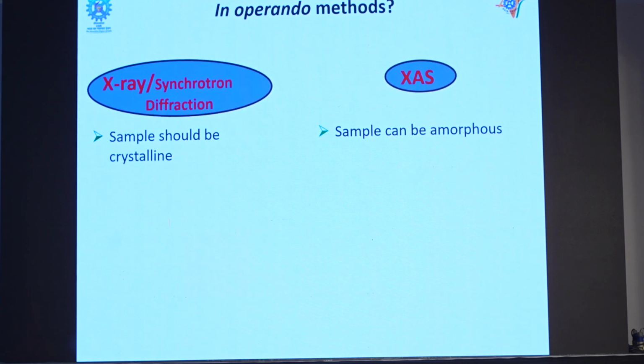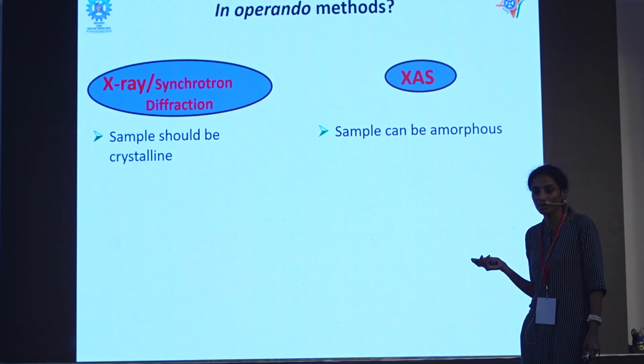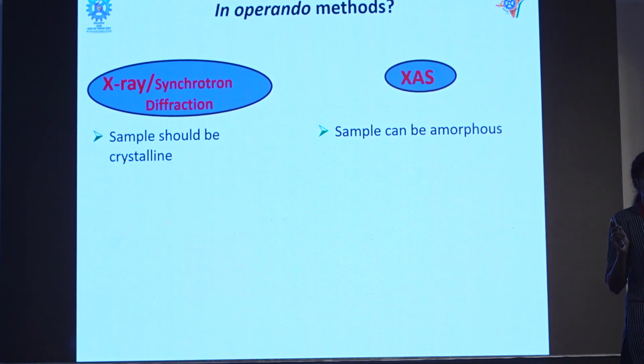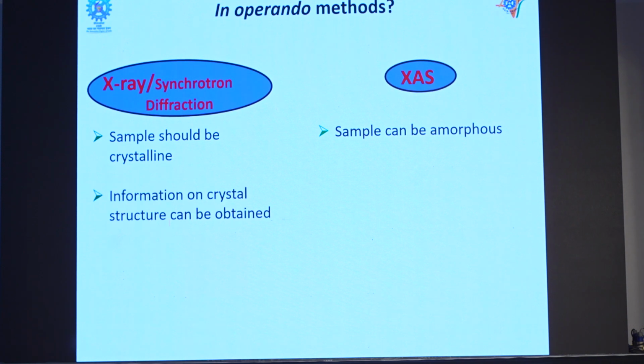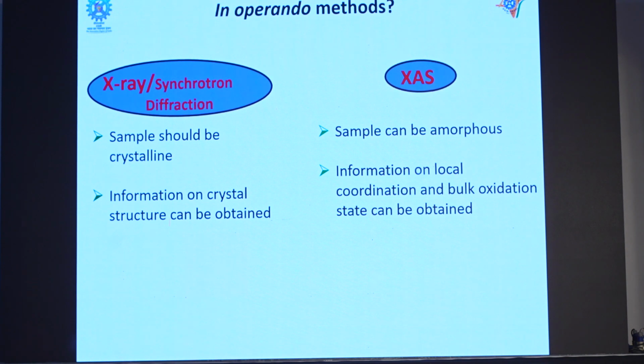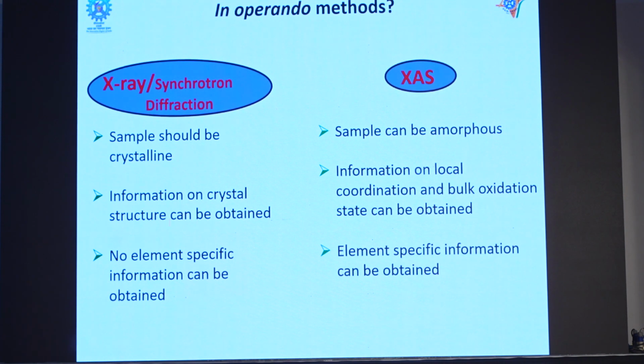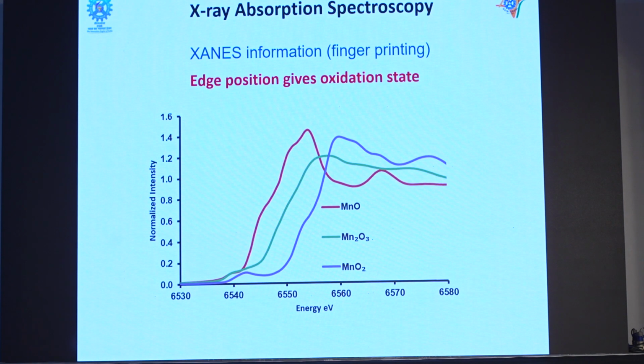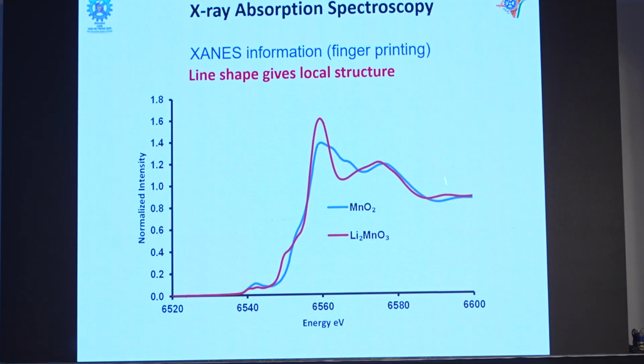And there are two different techniques we can do in-operando. One is an X-ray diffraction technique and one is an X-ray absorption technique. We did synchrotron diffraction instead of X-ray diffraction because it gives more accuracy and a higher resolution. For X-ray diffraction, the sample should be crystalline, and for X-ray absorption, the sample can be amorphous. In X-ray diffraction, we cannot get element-specific information, but with X-ray absorption, we can get element-specific information, all during operation. When you do X-ray absorption spectroscopy, we have an edge position which gives you the oxidation state, and then we have a line shape that determines the local structure.